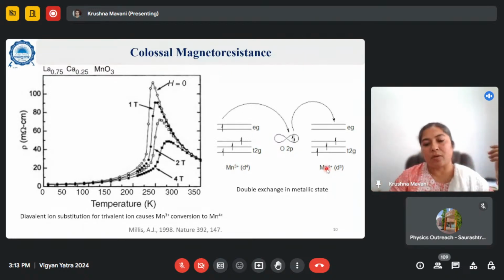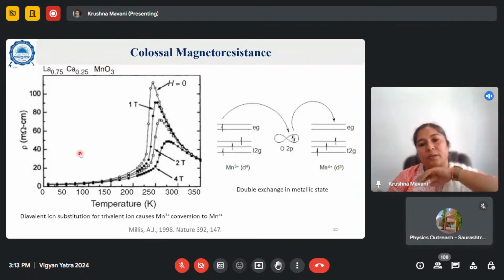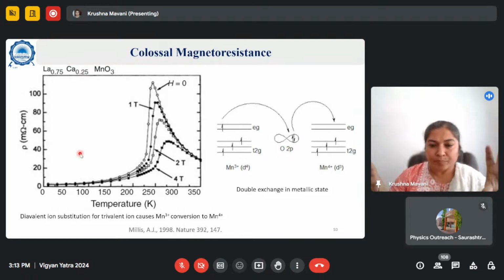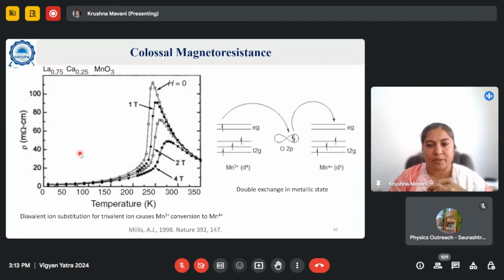While electron conduction is happening on application of an electric field, when an electron hops from here to here, this will become 3 plus and this becomes 4 plus, right? So there is another vacancy here, and the manganese on the other side can transfer the electron. So this is the scenario which is called Zener double exchange. A scientist called Zener proposed it and explained it.